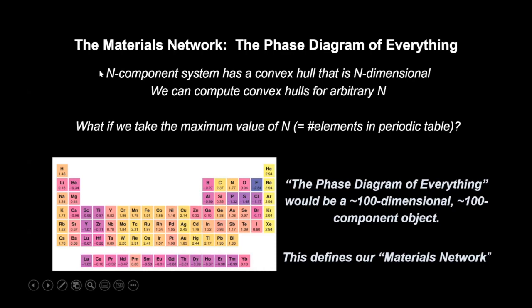And that is that if we're considering an n-component system, so n could be a binary or a ternary, n would be two or three, an n-component system actually has a convex hull that's n-dimensional, right? So the binary system had a two-dimensional convex hull. The ternary system had a three-dimensional convex hull, but we sort of projected out the energy axis. And then beyond that, it's very hard to even show you a convex hull. That's why I sort of map these things onto a graph representation.